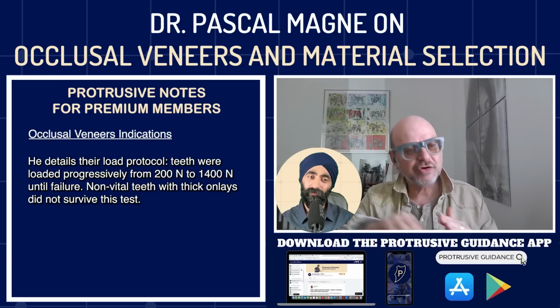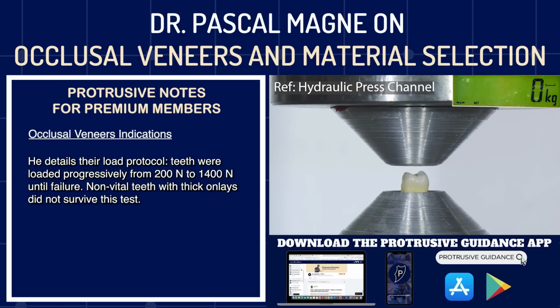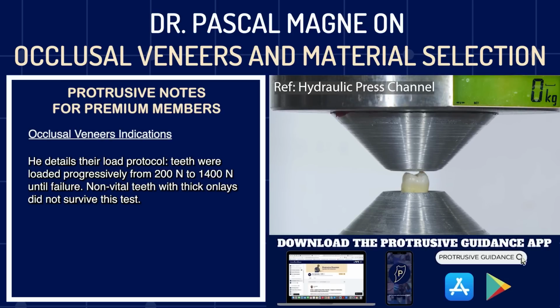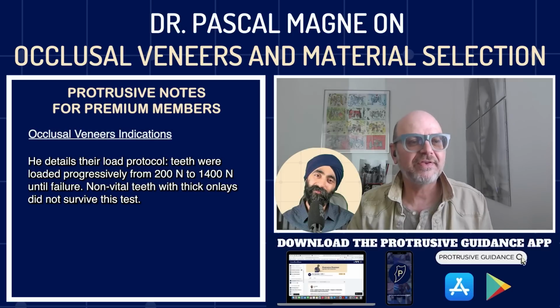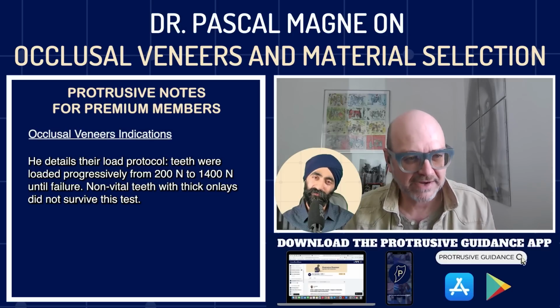And we have a load protocol that's well established. We start loading those teeth at 200 Newton, then we go 400, 600, 800, 1000, 1200 Newton. We keep ramping the load until we have a failure. And usually, I think we went to 1200 or 1400 Newton, and then we stop and we see how many teeth survived. Well, with non-vital teeth and those different onlays, we never had teeth surviving the test.